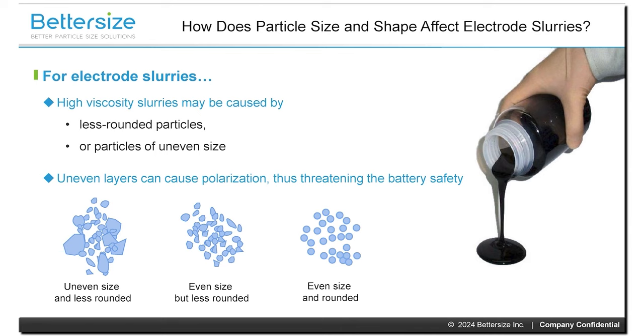We can affect electrode density and packing efficiency, with smaller particles achieving higher packing densities, and this maximizes utilization of the active materials, therefore the energy density. Certain shapes may enhance packing density or improve the accessibility of the ion diffusion pathways. In terms of electrochemical performance, fine particles provide higher specific surface area, and this facilitates faster ion diffusion and enhances better performance in terms of rate capability and cycle life. Shapes with high aspect ratios, for example, flakes, can offer shorter ion diffusion paths or better electrical contact, and this further improves the electrochemical performance metrics.